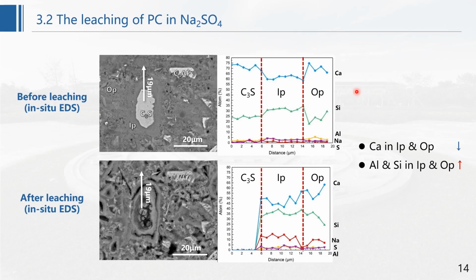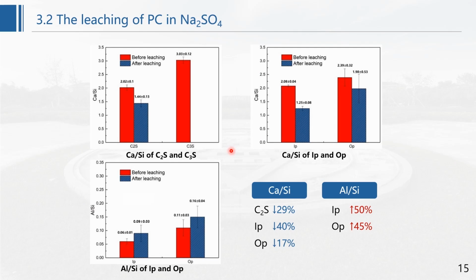Here are EDS results of PC paste before and after leaching in sodium sulfate. After leaching, the relative content of calcium in inner product and outer product both decrease, while the relative content of aluminum and silica in inner product and outer product both increase. Then we analyze the composition of different phases. After leaching, the calcium to silica ratio of C2S, inner product and outer product all decrease, while the aluminum to silica ratio of inner product and outer product both increase. This phenomenon is similar to that observed in deionized water.